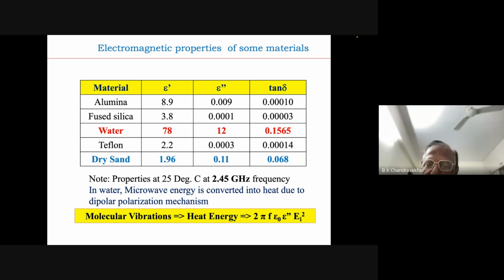It becomes transparent. If you look at alumina, again the epsilon double prime is very low, 0.009, and therefore alumina is transparent to microwave at room temperature of 25 degrees centigrade for 2.45 gigahertz.